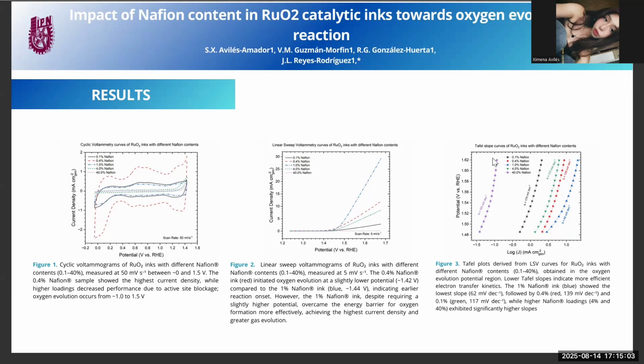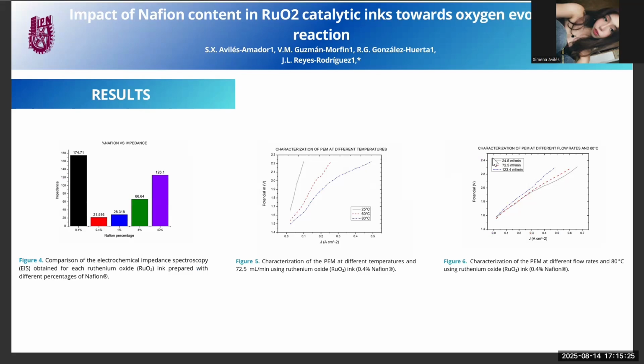Tafel analysis indicated that the 1% NAFION ink had the lowest slope, 62 millivolts per decade, suggesting faster electron transfer kinetics. The 0.4% NAFION ink had a slope of 139 millivolts per decade. Finally, the electrochemical impedance spectroscopy showed that the 0.4% NAFION had the lowest ohmic resistance. The 0.4% NAFION ink was chosen for membrane electrode assembly fabrication.